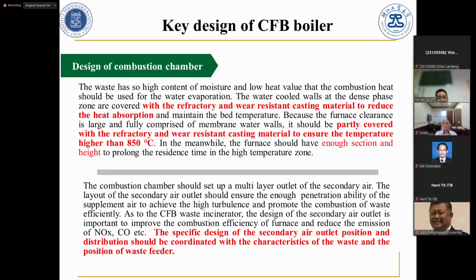So, design of the combustion chamber. The chamber means the furnace. Because the waste has a high moisture content and low heat value, the combustion heat should be used for water evaporation. In the furnace, we cover with refractory and wear resistant casting material to reduce the heat absorption. So it helps keep the combustion area temperature higher. We combust first, then we exchange the heat. So it should be partly covered with the refractory and wear resistant casting material to ensure the temperature is higher than 850 centigrade. This is like reducing the heat exchanger in the furnace to ensure the temperature.